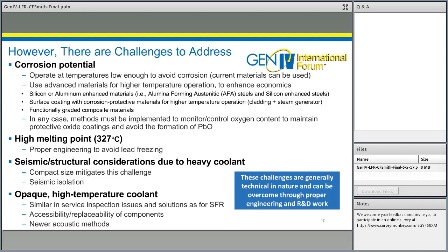A further issue is the fact that lead is an opaque, high-temperature coolant, and this has implications for in-service inspection as well as other operational requirements. There are similar in-service inspection issues and solutions with the sodium fast reactor, which is also an opaque, high-temperature coolant. So some of the methods developed for the sodium fast reactor will also apply to the lead-cooled fast reactor. An approach for several LFR concepts is to emphasize and implement accessibility and replaceability of components, which can allow for periodic inspection out of the lead coolant. Finally, there are newer acoustic methods that are being discussed, studied, and appear to work well for lead-cooled systems.